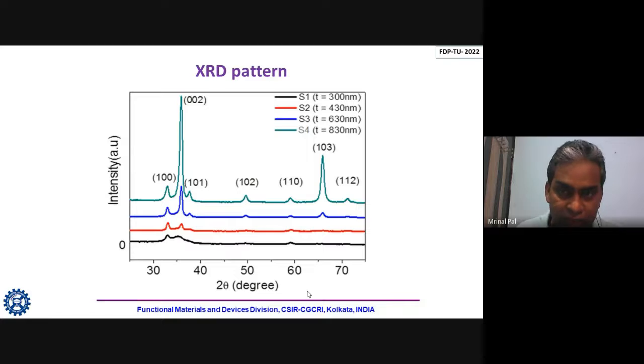You see, for this black one, which is the thinnest, 300 nanometer thickness, the peaks are just coming. One may say it's kind of amorphous. But when you increase the thickness, slowly the crystallinity appears. And you see for S3, which is blue, and S4, which is green, all the peaks are very prominent. So if you make a thin film that is really very thin, you can end up with this kind of amorphous thing. And if you go on increasing the thickness, then you can end up with a crystalline film.